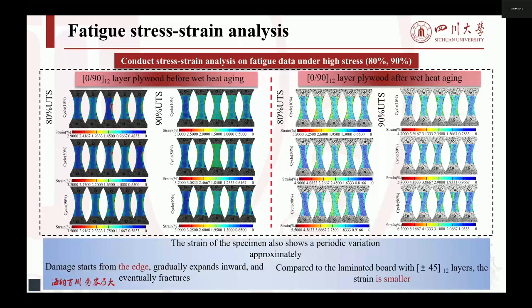For 90-degree laminated boards, it can be observed that damage begins at the edges and extends inward. This is due to fiber debonding caused by hygrothermal aging, resulting in uneven stress distribution. Additionally, the strength of hygrothermal aged 90-degree laminated boards is less than that of 45-degree laminated boards.